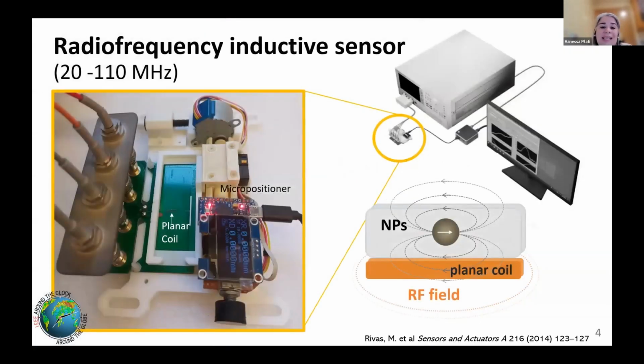To detect the magnetic nanoparticles in the test line, we are using radiofrequency inductive sensors in our lab. This is the sensor we have now. Here we have a planar coil and a micropositioner. This was specifically developed for reading magnetic lateral flow assays. The circuit is linked to an impedance analyzer that monitors the impedance of the circuit.